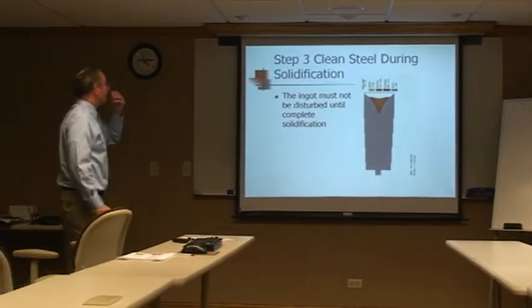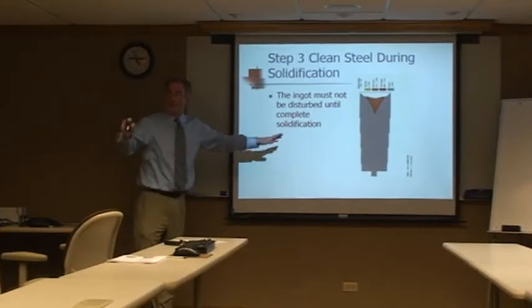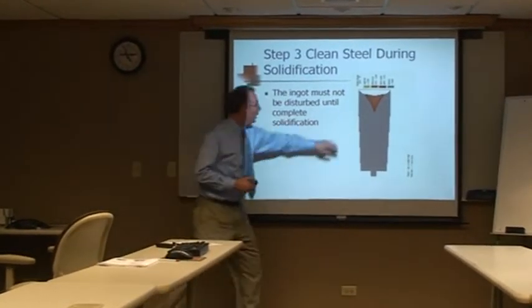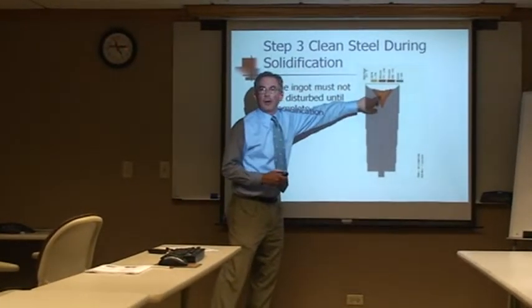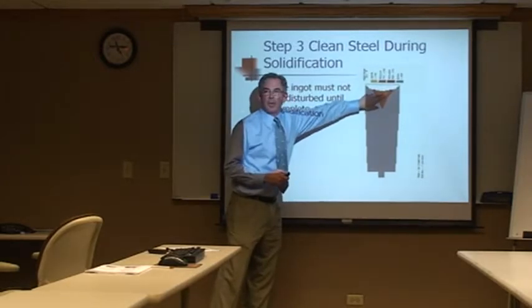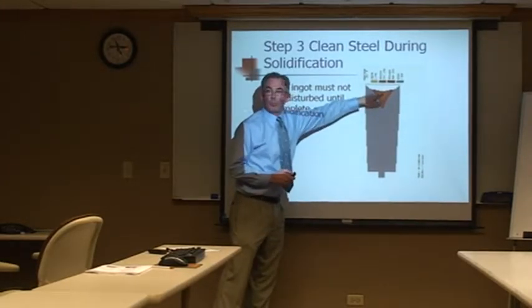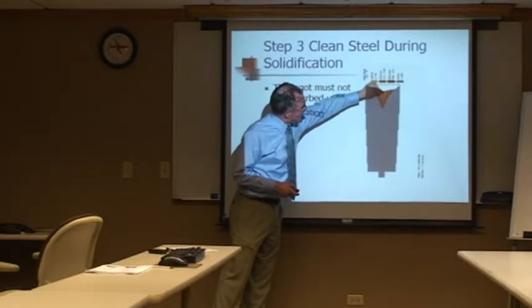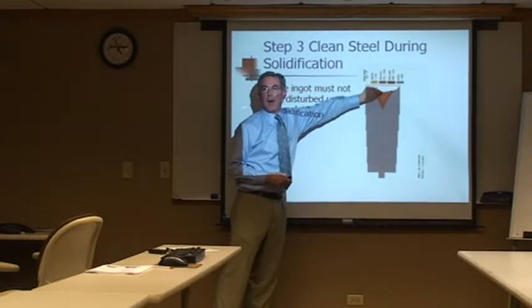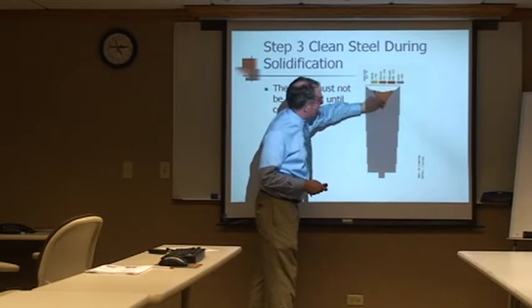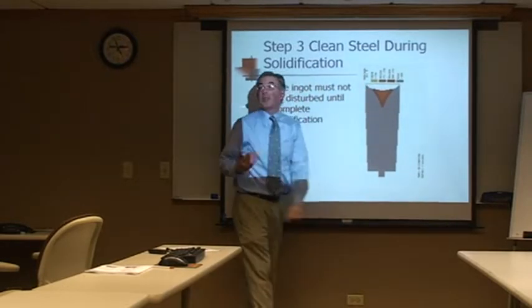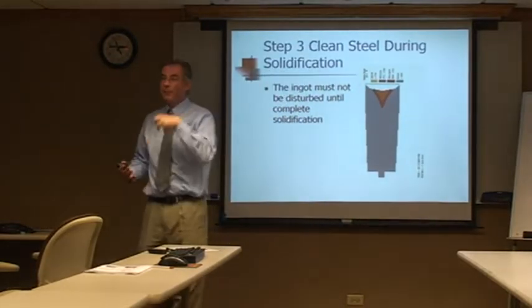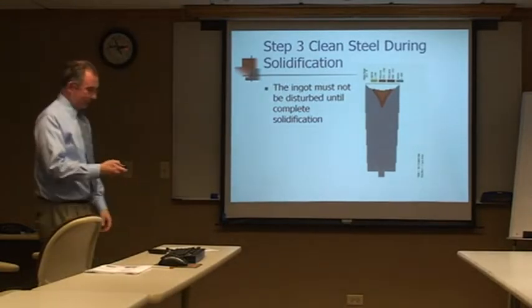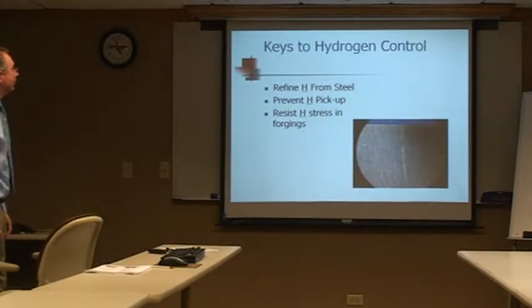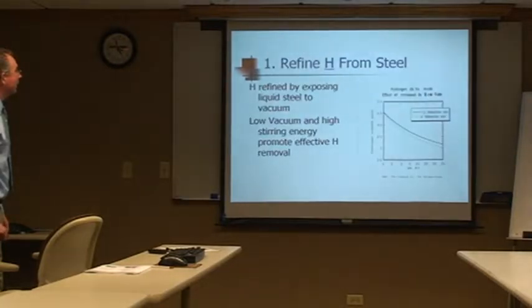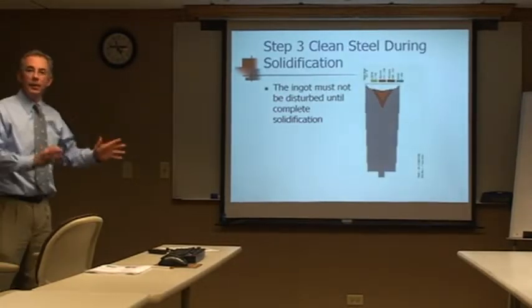And then finally, clean steel during solidification. We talked about this the whole time, making sure we don't disturb it. If we were to strip it early, or cut it early, this is still a mushy zone. So if we bump that, all that work and flotation is lost. This last metal to solidify is a little time bomb sitting in there. So we don't want to bump it and allow it to move and possibly end up getting disturbed and freezing below the hot top junction. And that's it on the clean steel portion.